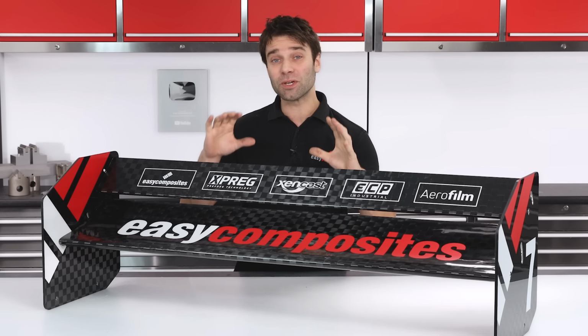The resin can then be driven up into the fibre using a finned roller. Working the resin up through the laminate like this, rather than trying to wet out the fibre from the back, helps to reduce the amount of air that's entrapped and will produce higher quality parts.